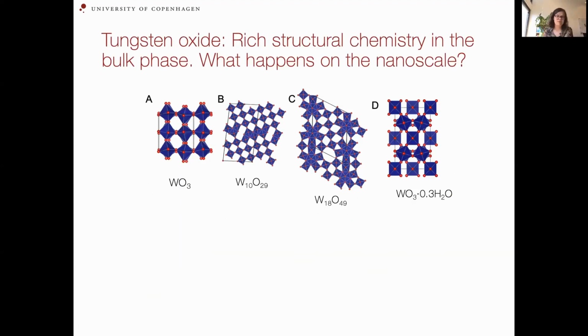For example, a material that we have studied quite a lot is tungsten oxide. Tungsten oxides have lots of applications, for example, in photocatalysis, but also in battery science. And it can be synthesized in quite a lot of different polymorphs, meaning that we can make different crystal structures. Here are just some that are shown, that we can look up in databases: the fully oxidized tungsten oxide, these non-stoichiometric phases, and a hydrate. These are just examples of what can be made, and they have quite different properties. So it's important that when we synthesize the materials, we know what we're getting.